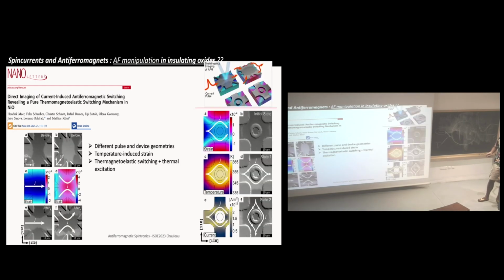I'll do this quickly. When you shine a huge current like this, you also have an anisotropic strain. And since NiO is also magnetostrictive, if you have an anisotropic strain, so you don't strain the same way in one direction and another, then you will start rotating the T domains. This has been proven here because they made a cross and then cut out a circle, so there is no current flowing there, and they could switch anywhere in the middle, even if there is no flow of spin current. So there was the proof of this.